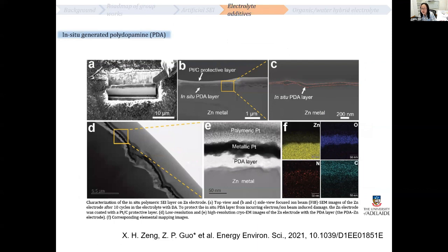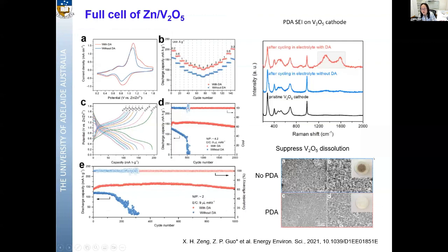The inorganic one is normally about 150 nanometers, even sometimes achieving a few micrometers thickness. So this is very important because a thinner SEI can save space and without sacrificing the volumetric energy density of the battery. So this is another advantage of this in situ polymer SEI.